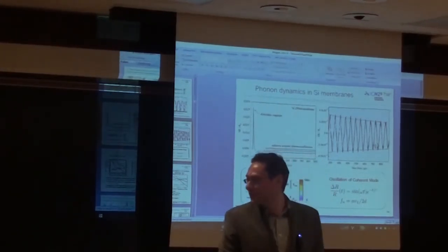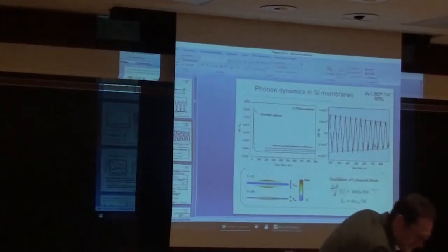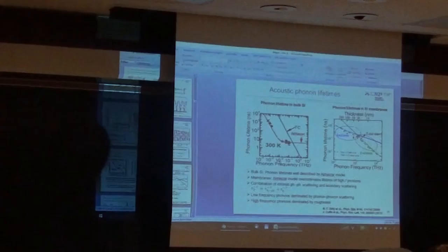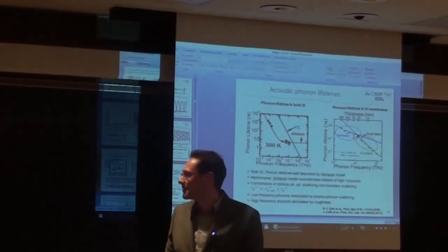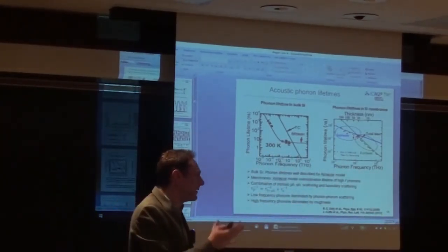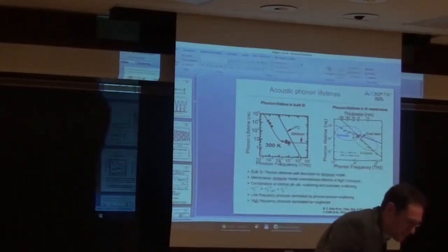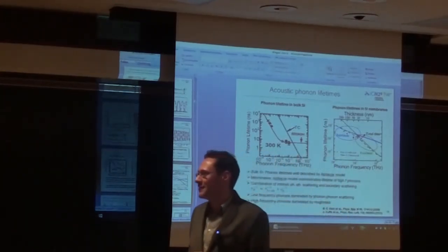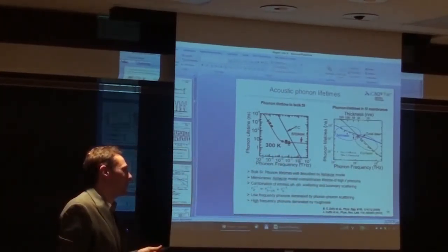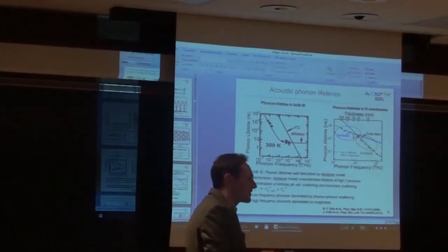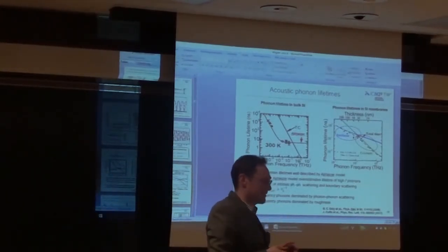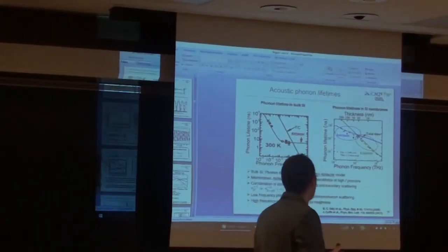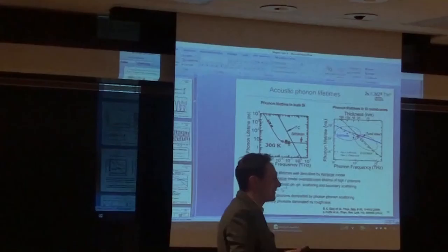but of course you can use transducers, like the group of David Cahill did already in 2009, using a transducer and then looking at bulk silicon, measuring the phonon lifetimes and so on. That is in principle possible, but I'm not sure how largely you can strain bulk material, because you can probably put it in a hydrostatic pressure cell and apply a lot of hydrostatic pressure, but I would expect this Akhiezer mechanism to be very temperature dependent.